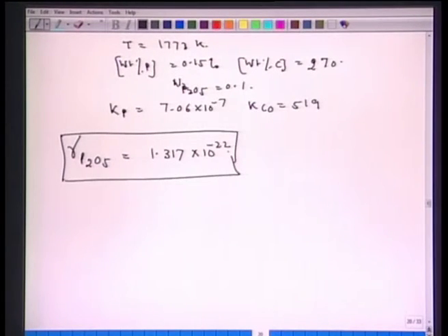What does this suggest? Simultaneous removal of carbon and phosphorus is possible only when the activity of P2O5 is drastically reduced; then the carbon reaction and phosphorus reaction can take place together.